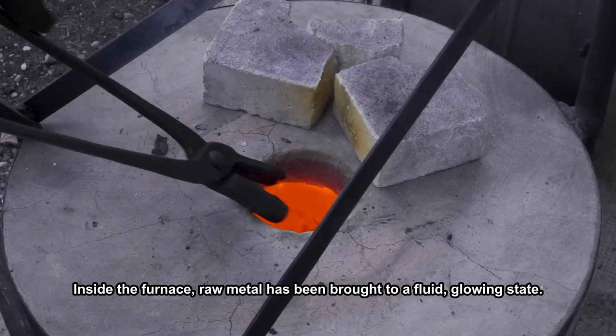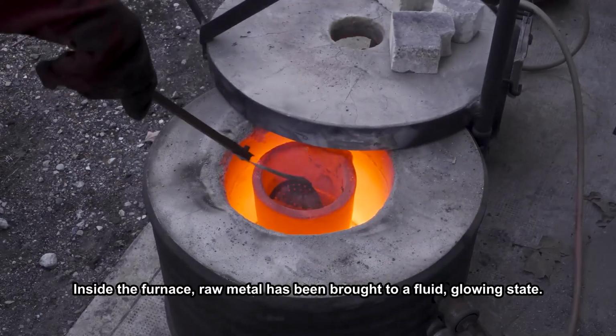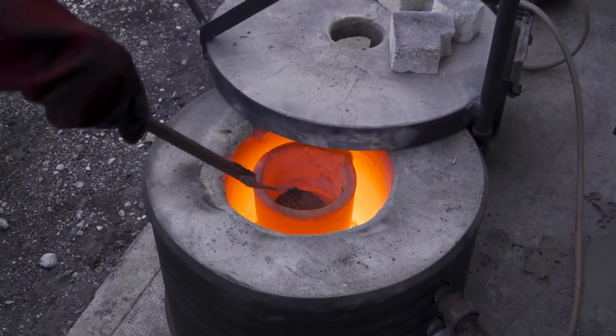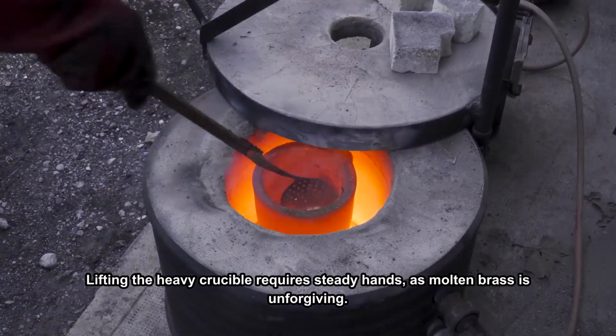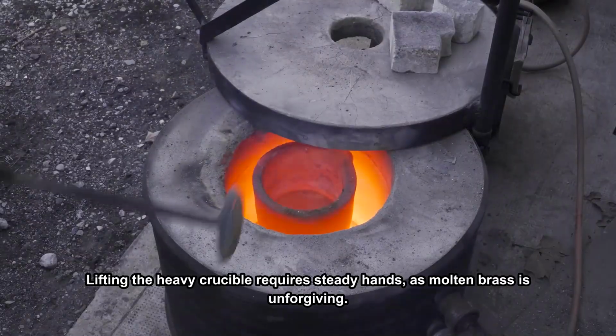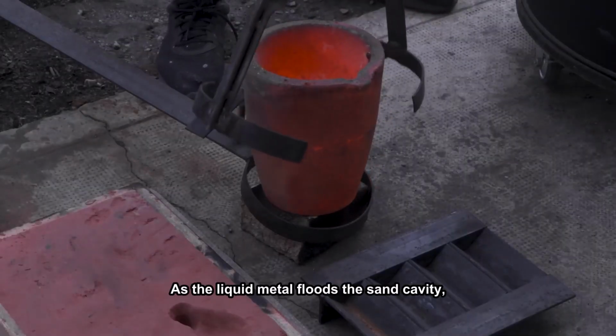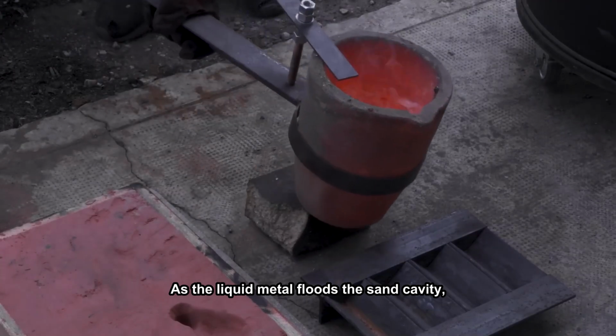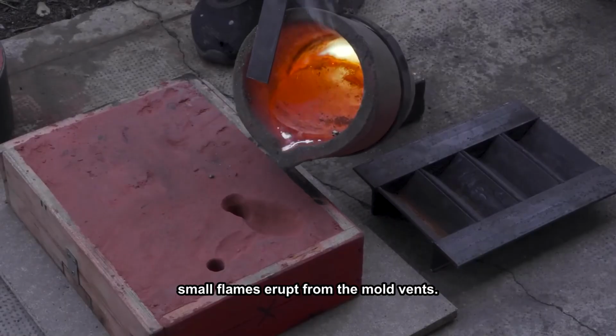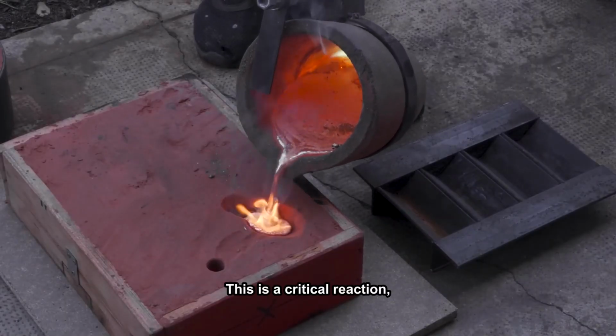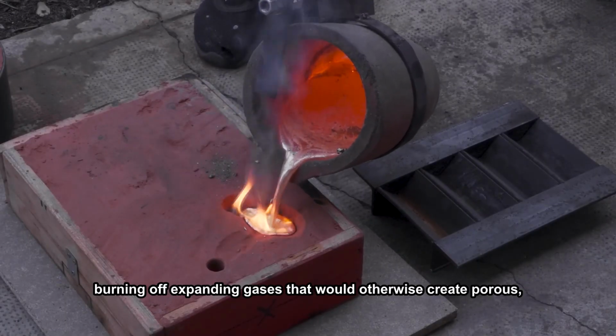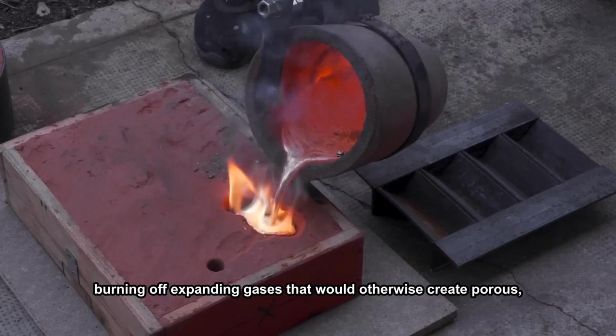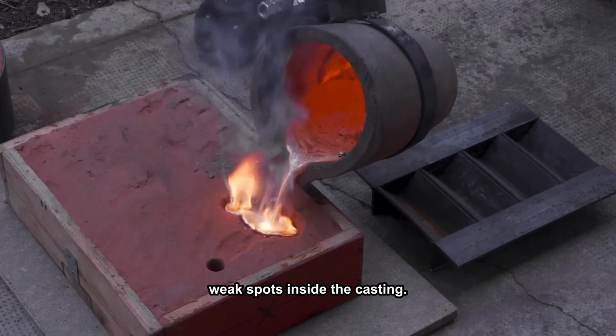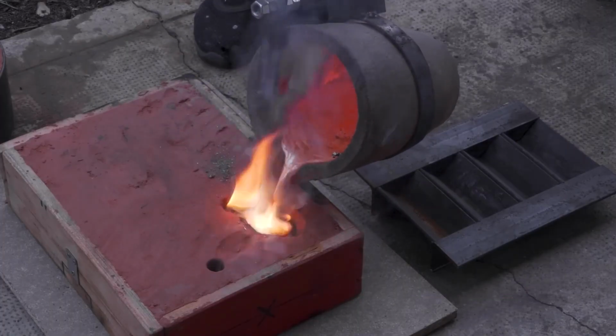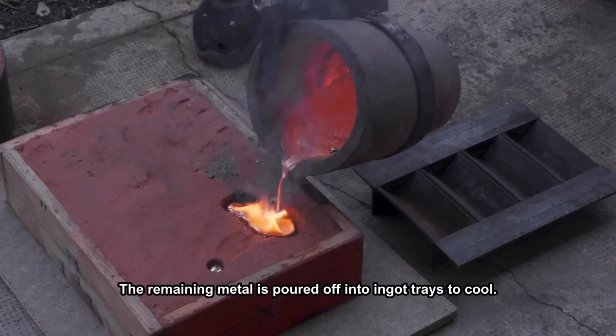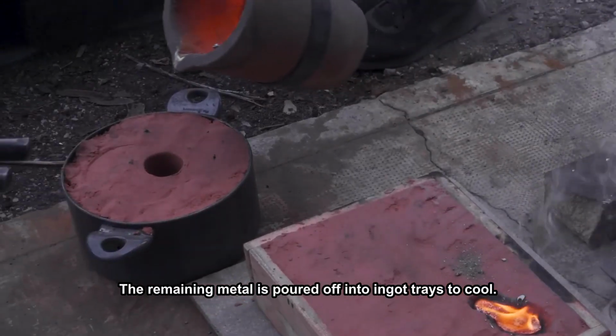Inside the furnace, raw metal has been brought to a fluid, glowing state. Lifting the heavy crucible requires steady hands, as molten brass is unforgiving. As the liquid metal floods the sand cavity, small flames erupt from the mold vents. This is a critical reaction, burning off expanding gases that would otherwise create porous, weak spots inside the casting. The remaining metal is poured off into ingot trays to cool.